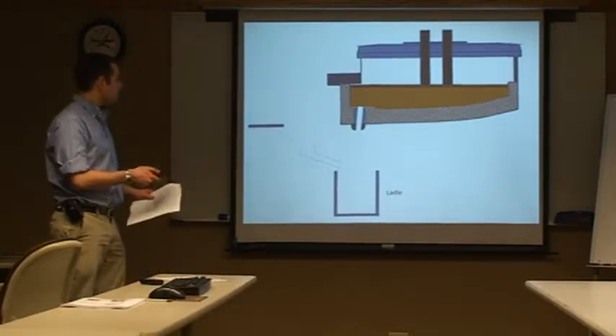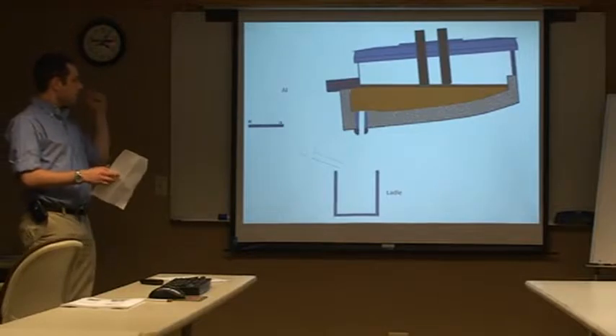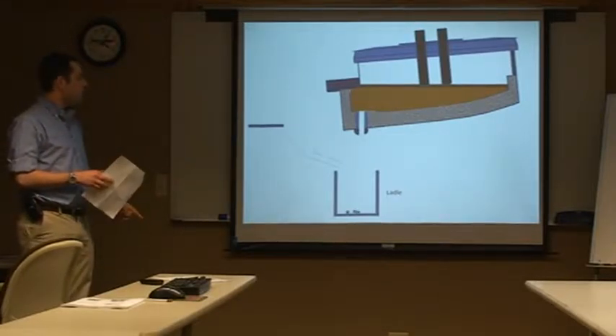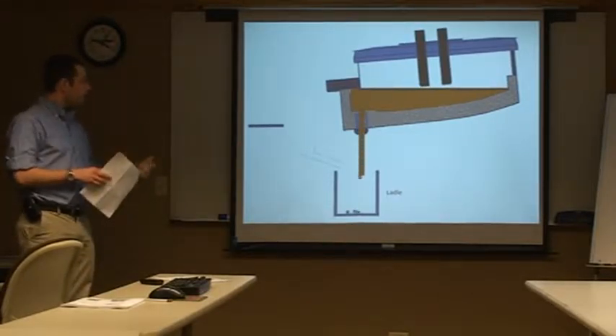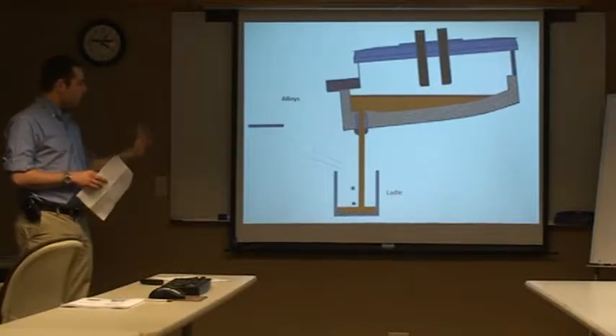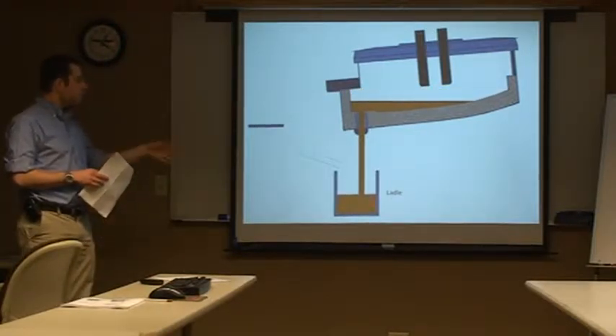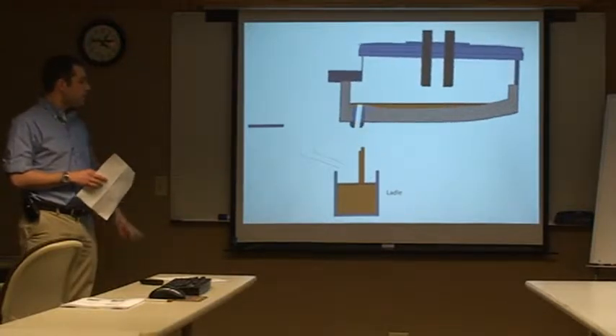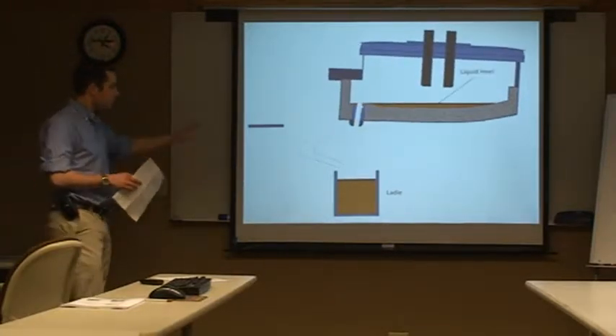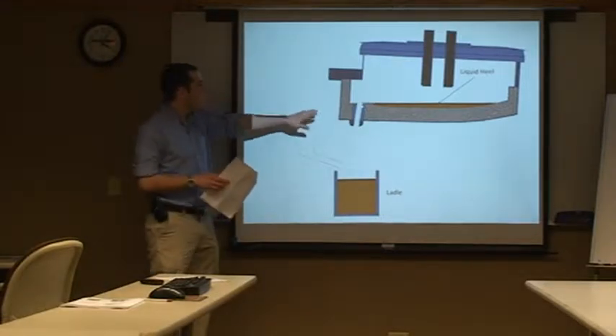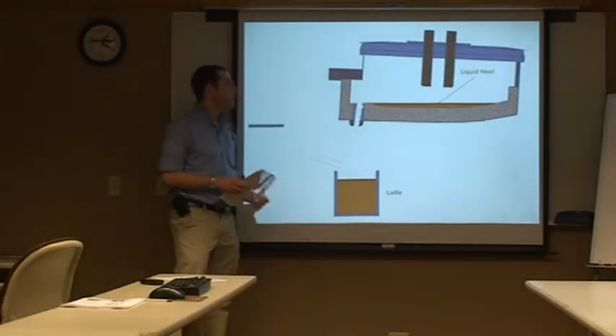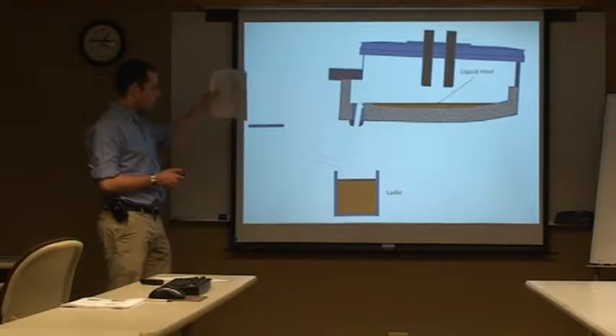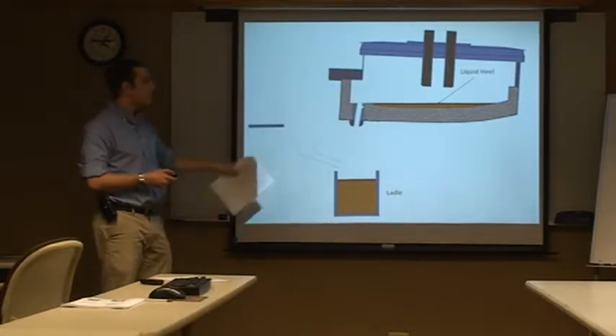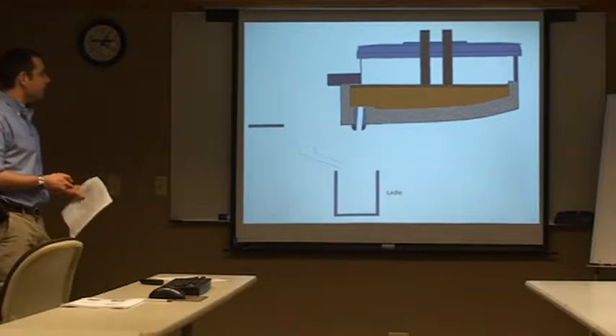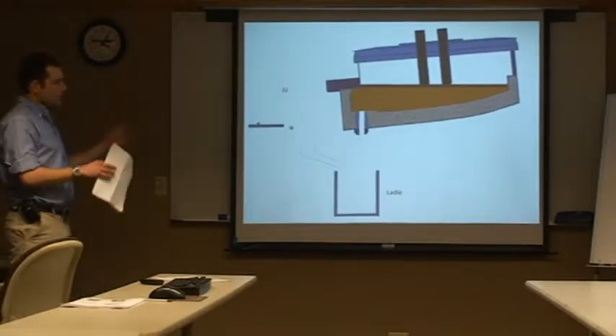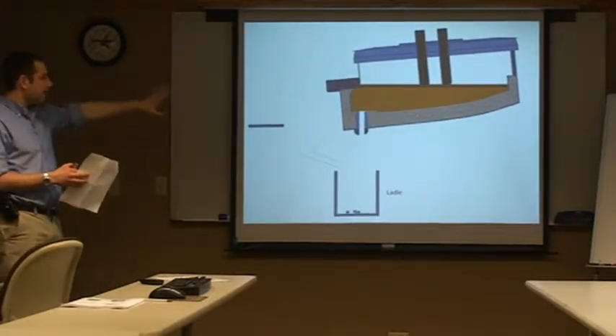So here we go. The furnace is tilting, we put our aluminum in there. Now it starts to tap. Put in some alloys. Also throw in some lime to generate a slag cover. And if you saw, we tilted the furnace back before the slag level, which is this brown part, got down to the level of where the spout was. I'll just rewind and show that again so you can see that. We want to tilt the furnace back to keep that arc furnace slag in the furnace.